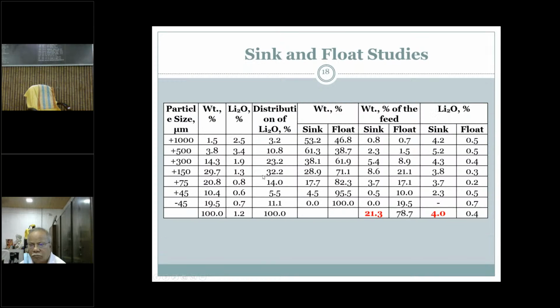So what we have done, we subjected the sample to sink and float studies, and here are the results. You can see the second column is again the weight percentage, then the lithium content, and the fourth column is the distribution of lithium amongst the size fractions. You will find the intermediate size, especially in the size range of around 500 to 75, has the maximum distribution of lithium content. Each size fraction has been subjected to sink and float. You will find in the sink and float columns, the sink fractions go on decreasing, and the float fraction goes on increasing with respect to particle size.